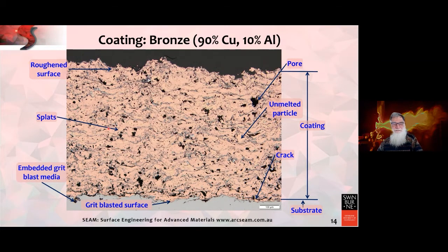We see splats, which are like pancakes laid on top of each other, or saucers, or bricks. Embedded grit from the blast media is often observed. It's not bad, you just have to control it. You have the grit blasted substrate. We have cracks which are lamellar. If we look very closely, I'm trying to find cracks which are vertical. Possibly there's one there. We have unmelted particles and we have porosity. So that is the taxonomy. This is how we break up a coating structure.